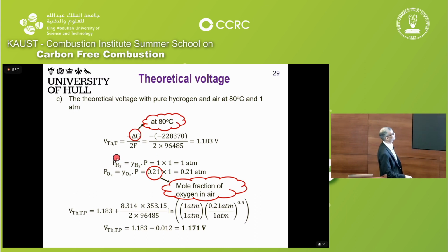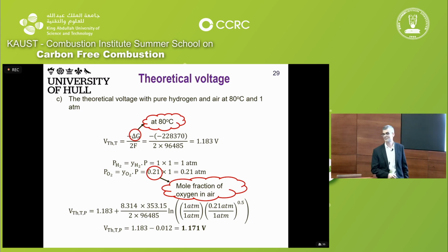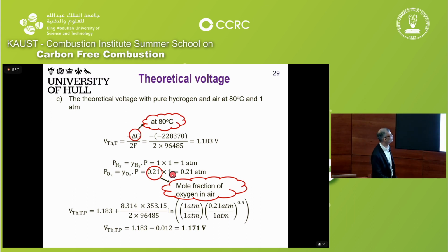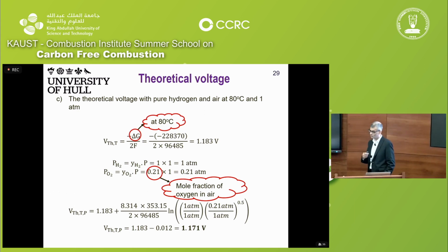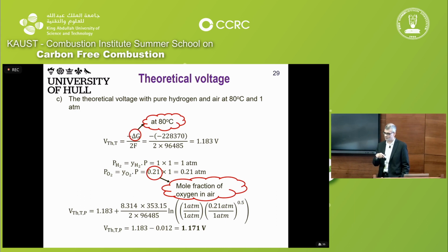Here, the theoretical voltage for a given temperature is the same as the second case, which is 1.183 volt. The partial pressure of hydrogen is the same as the first case. The partial pressure of oxygen is going to be slightly different this time because we are using air, and the mole fraction of oxygen in air is 21%. So the partial pressure of oxygen is 0.21 atmosphere. If we plug these numbers into the Nernst equation, we would notice that the theoretical voltage has decreased compared to the second case by around 12 millivolt. Meaning that it's always better to use pure oxygen, but on the other hand, it's more expensive.